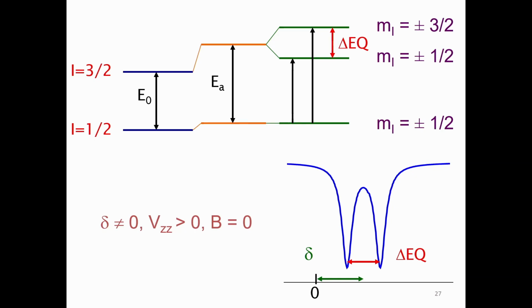So now we have first the isomer shift, which corresponds to the center of gravity. So it is given here, the distance between the center and the zero. And you have the splitting, which corresponds to the distance between the two lines, and also to the distance between the two sublevels.